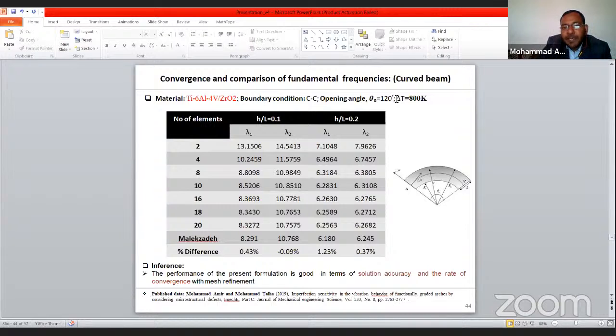Here the temperature dependent material properties are considered, and delta T is considered as 800 Kelvin. For the curved beam, the first two modes of the frequencies are presented and compared with the reference result for two different h by L ratios, and we found that there is a good agreement between the results, as well as it converges at n is equal to 20, the number of elements.